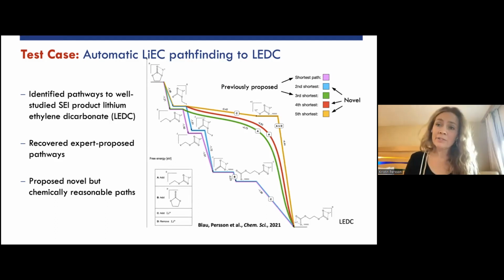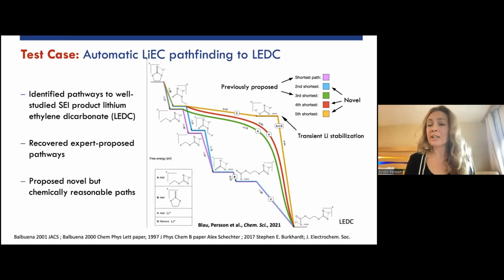We also find other, novel paths. They're not tremendously different; they're variations on Perla's path, but it makes sense that if you have something that is spontaneous and really downhill in delta G, you are going to find slight variations of this. There are many paths to Rome. One of them that I like is this slightly unintuitive ring opening, where an intermediate is stabilized by a lithium that swoops in, stabilizes a bond breaking, and then swoops out again. That seems quite likely to happen in the bath of the electrolyte, in these cascade reactions that happen close to the anode when you get the first SEI formation.